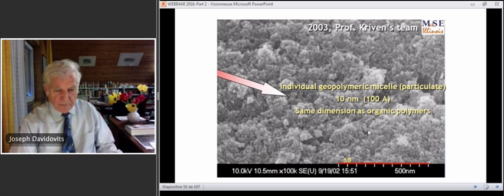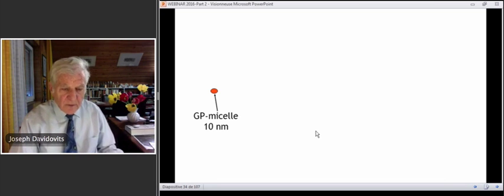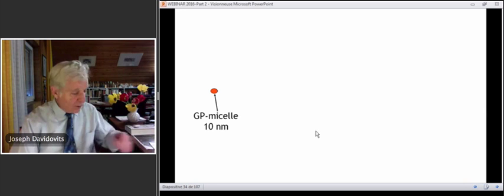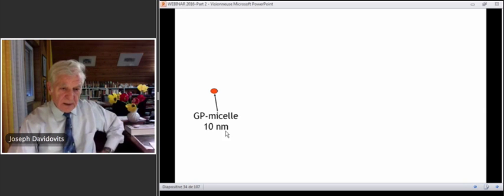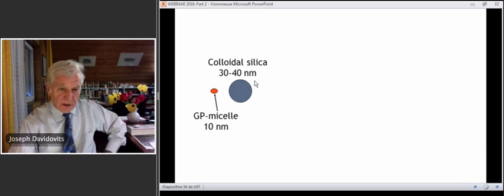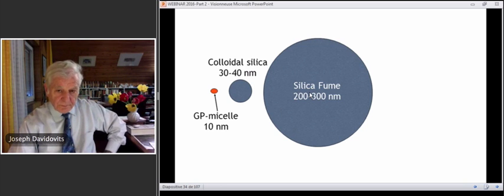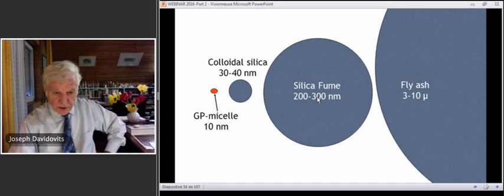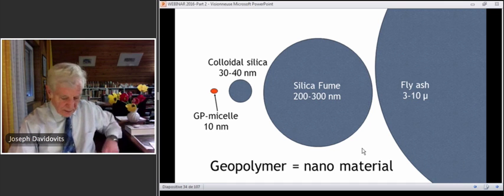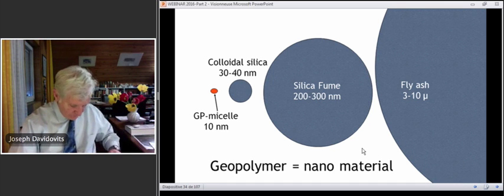And we are making polymers, and it is obvious that we end up with structures that are related to polymers. If we compare the dimension of the geopolymeric micelle, the particulates, 10 nanometers, this is colloidal silica, then we have silica fume, and then we have the fly ash, which is a monster. The geopolymer is a nano material.